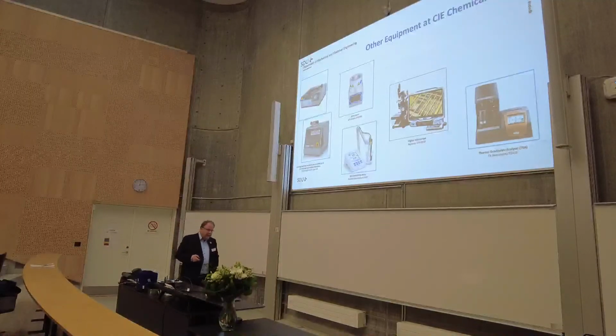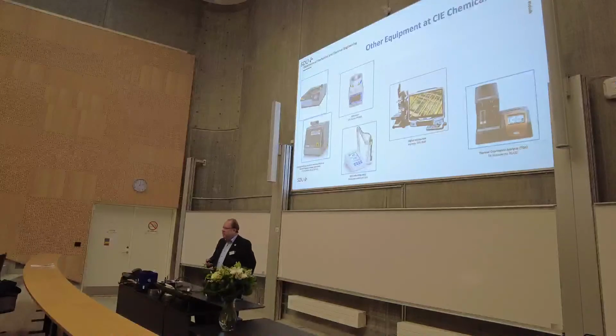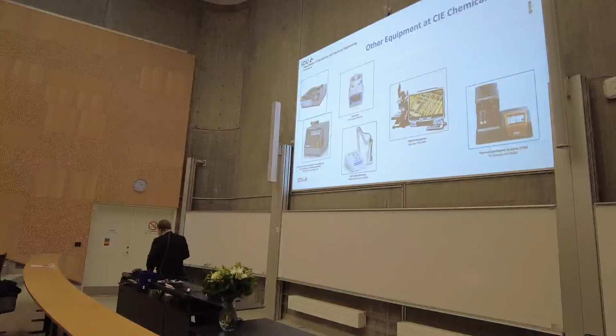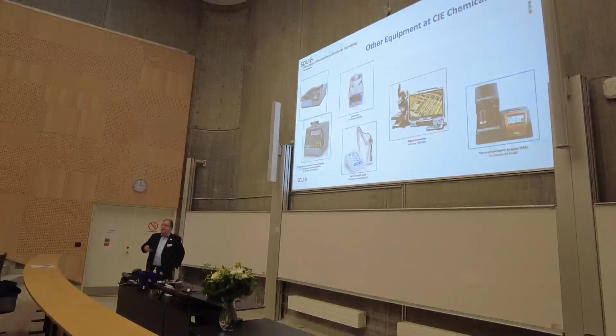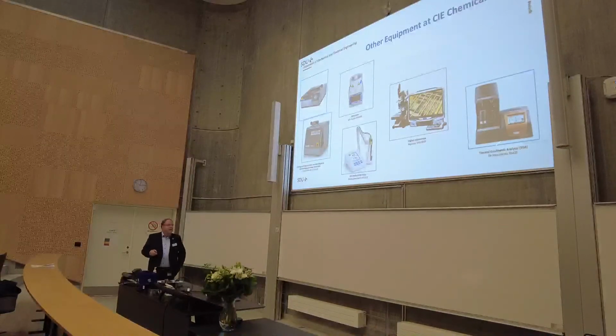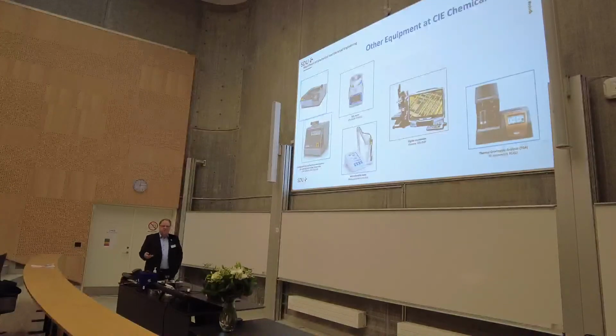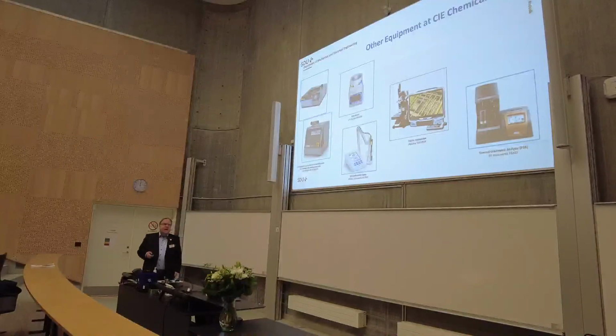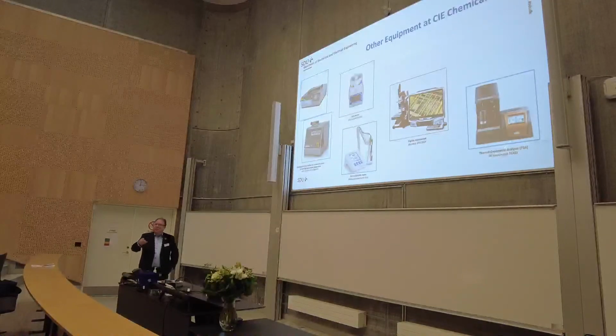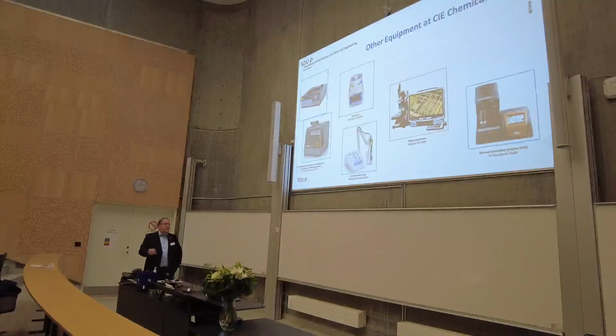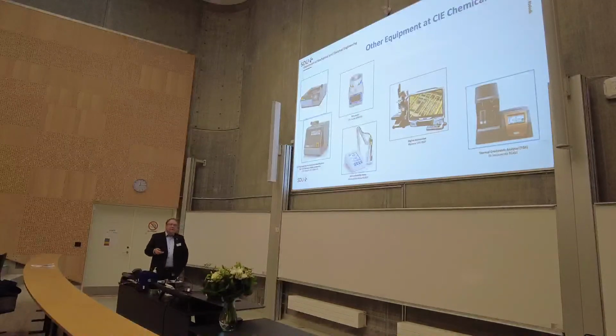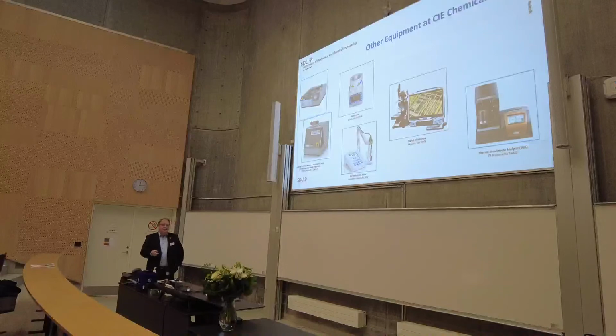Another topic I would like to discuss is polymer investigations, based on polymer metallized film capacitors. They are one of the driving components in windmills, for example, and they are also exposed to certain deterioration reactions. And we have now invested in a gravimetric analysis method called TGA. In fact, it's a kind of balance where you can expose, for example, a polymer to temperatures, and then you see how, in dependence of the temperature, a certain polymer is deteriorating, and we can measure the weight loss with this system. And now we can attach this also to our mass spectrometer. So we also get defined mass loss information during load operation in metallized film capacitors.